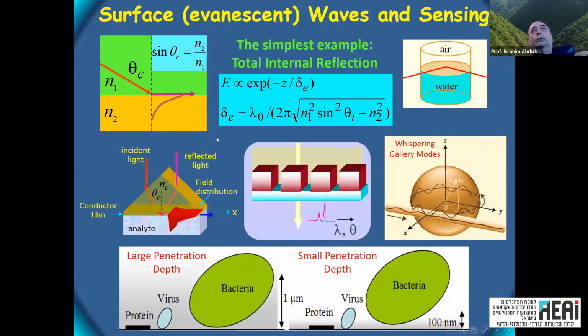We can calculate easily what is called the penetration depth, and it decreases as we increase the incidence angle. It can be as small as lambda over 10 or even less. And we can see this effect in many other optical phenomena. For example, what's called whispering gallery modes, where we have these waves circulating a sphere. We can excite surface waves.